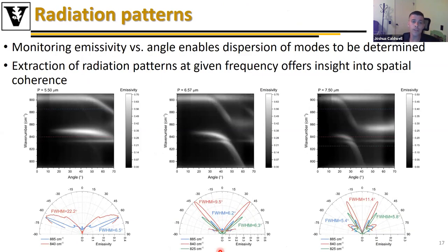So now if we look at the overall radiation patterns from these, you can see from these dispersions, if I choose any specific angle or specific mode, I can now pick out how that mode is radiating. So you can see this guy here, which is coupled to this grating mode, I get a relatively narrow angular spread. Whereas in the strong coupling regime, this is somewhat broadened. And now I can start to probe what is it about these various interactions that allows me to induce a given desired angle of emission and also narrows that angular spread.